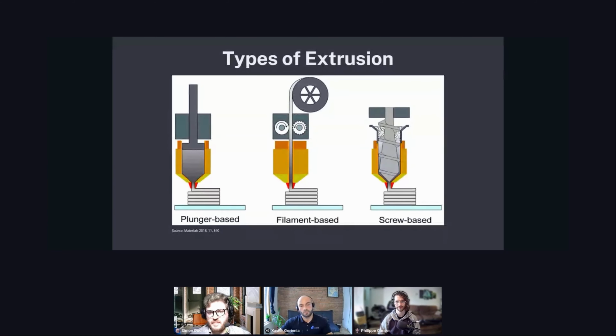So on the left, it's the plunger base, where you are using a syringe or a pump to generally extrude paste or clay or biomaterial and any fluid-like materials. The middle one is the filament-based extrusion, the most common type in the industry, where you are using a polymer or a composite filament and driving it through a geared extruder. And then finally, there is the screw-based type, where you use powder or pellets. Basically, it's a motor that is turning an endless screw to move the material all the way through the melting zone.